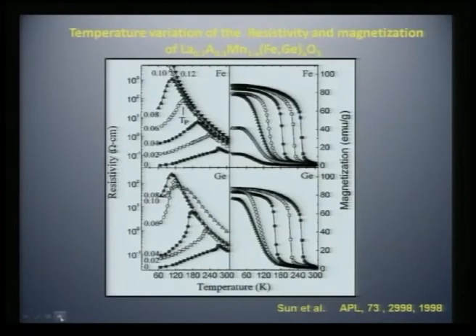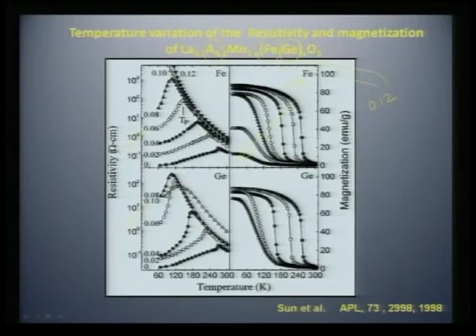In the next slide, I will show you, suppose I substitute iron or germanium in manganite, where I am going to keep this A value constant. A is constant, therefore anything that happens will be as a result of iron or germanium. What happens here? These are the two magnetization versus temperature plots. These two cartoons show the resistivity change as a function of temperature. As you see here, when you dope iron starting from the parent compound, you can clearly see that the TC decreases as a function of iron, up to 0.12 iron, which means just for 12% of iron substituted in manganite, you almost kill the ferromagnetic ordering.